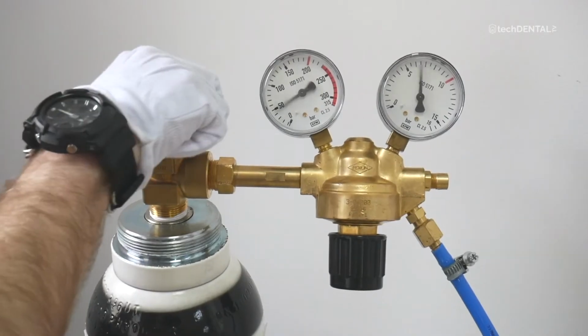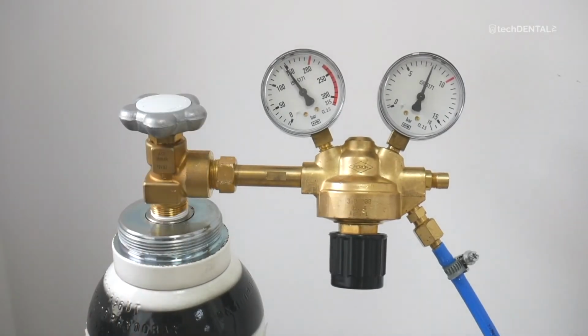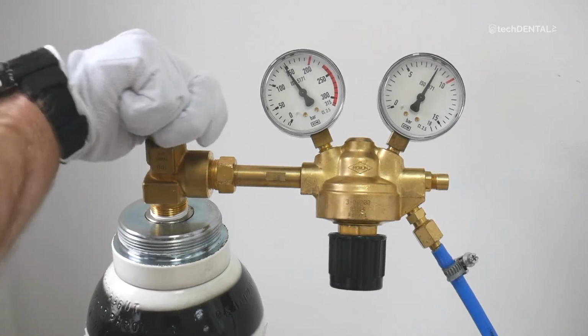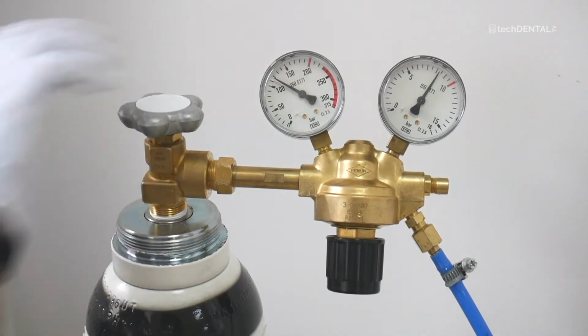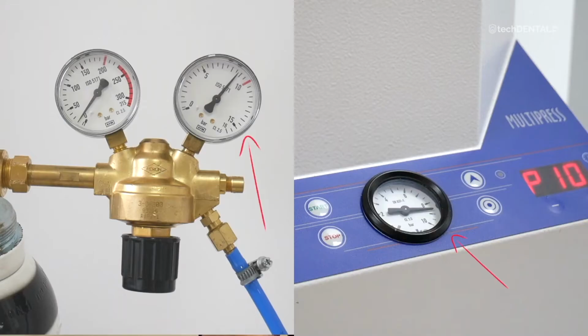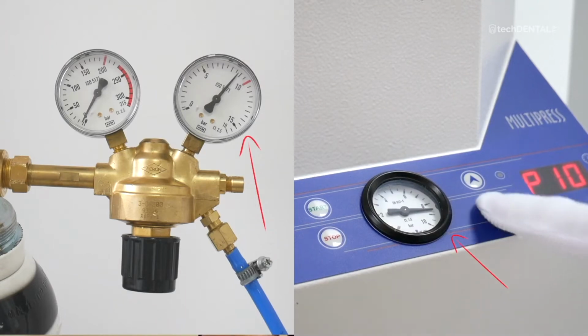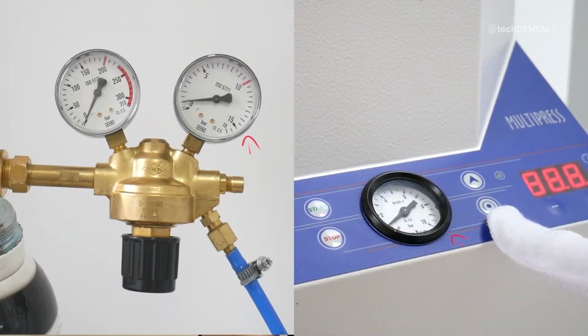There may also be a situation where your colleague used compressed air for sandblasting, and at the time of injection the pressure on the injection machine was much lower. On the other hand, when you use a cylinder, you often forget to unscrew it. After the injection is finished, you turn off the cylinder. When re-injecting, the gauge shows the correct level because the pressure remains in the lines. But at the time of injection there is too little pressure to fill the actuator. Always check the pressure exactly at the time of injection.